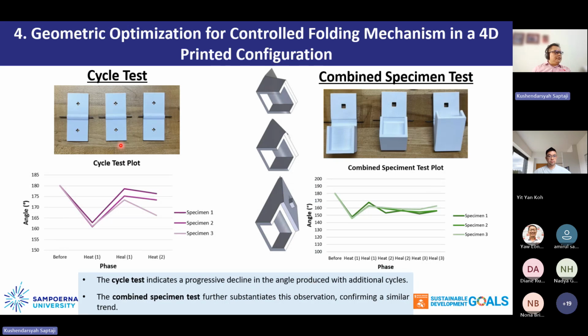We also do the cycle test to make sure that we can apply this technique consecutively a few times. From the cycle test, we heat up once and then we heal, which means we heat up again, so it goes back to original, and then we heat up again, and you can see the angle is changing. So we still need to improve this cycle test. We also make this combined specimen test to replicate the package shape, and then we also do the cycle test. This step is still in process.